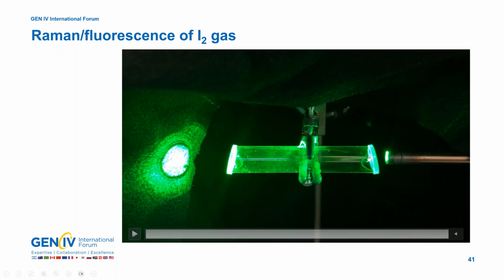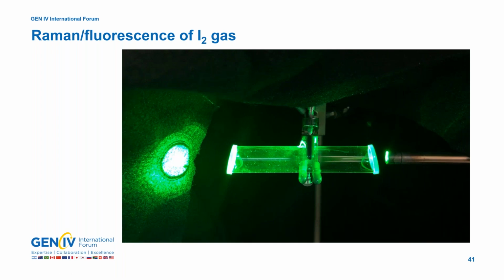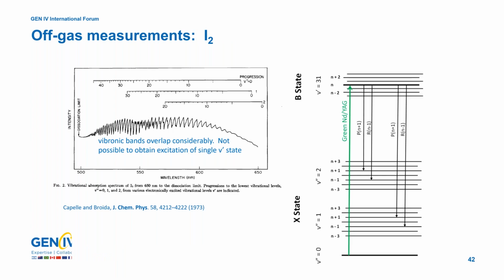We saw that and we said, oh, this is really great. What we intended to do is measure the Raman spectrum of this I2, but in addition to the Raman measurement we also got this very sensitive fluorescence band coming out. What that fluorescence is due to: this is a spectrum from the literature of iodine in the gas phase, the UV-Vis spectrum, showing a nice vibronic progression, a lot of vibronic bands on top of this absorption band.